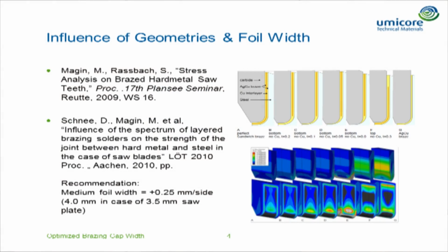But besides these products on the market which can protect the saw tips, we can still see some failures in the industrial field. For example, here you can see an uneven and inhomogeneous copper layer in between. These kinds of failures were investigated some years ago by our colleagues Magin and Rasbach, and the results of this finite element analysis were presented in 2009 at the Plansee Seminar.